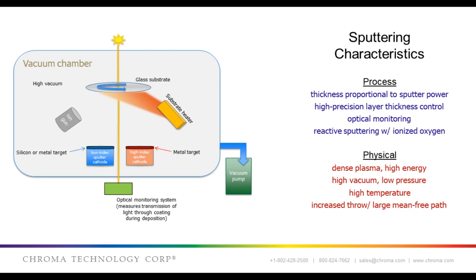You can see the optical monitoring system, which provides feedback for the deposition in terms of an optical signal, which ultimately is what matters. Now we see the high-index material going. Sputtering begins as the power supplies go on. In this case, ionized argon forms the plasma. The sputter material moves along a ballistic path between the target and the substrate. At low pressures, the atoms carry almost all of their original energy to the substrate. The sputtered atoms form a vapor cloud, or deposition cloud, which then condenses on the substrate.